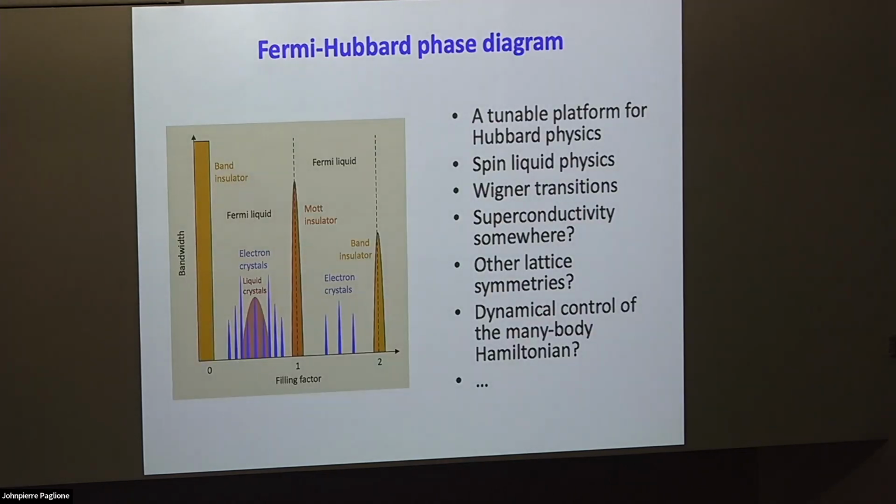To me, it seems it's probably just my definition of whether we should call them an electron crystal or a density wave. In the zero bandwidth limit, it's almost like only classical electrons, the Wigner limit, like a Wigner crystal. The electrons are like point charge particles, except for the spin, and they are well localized by the lattice. Then the Coulomb repulsion would just self-organize them into a periodic pattern.